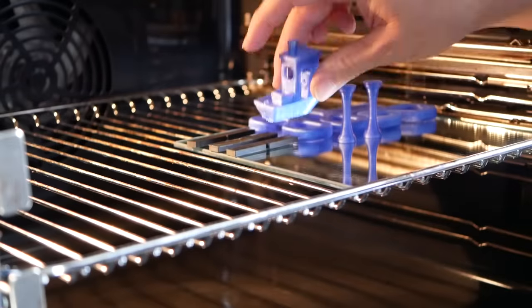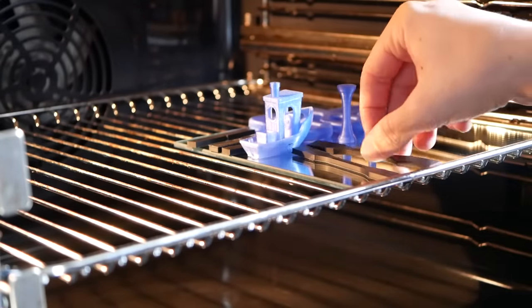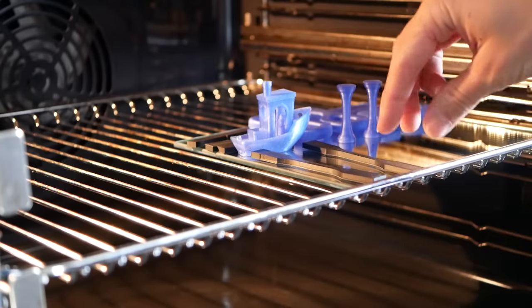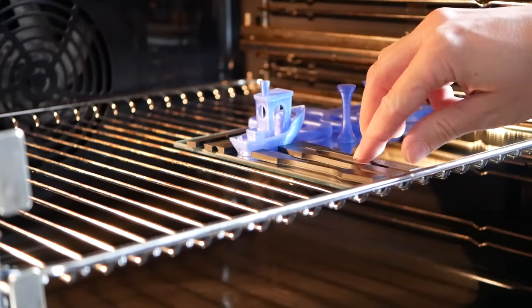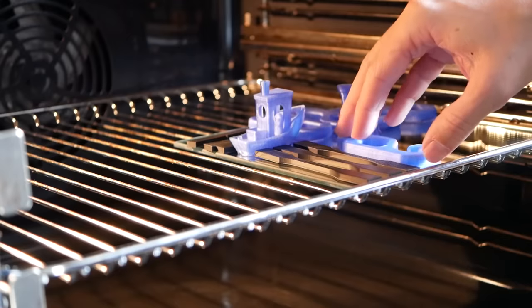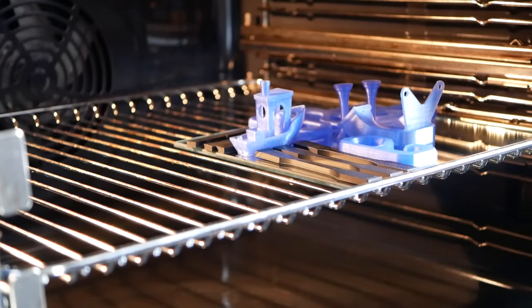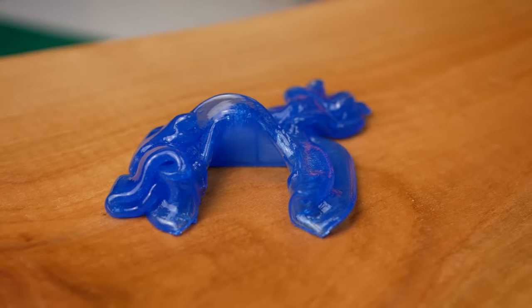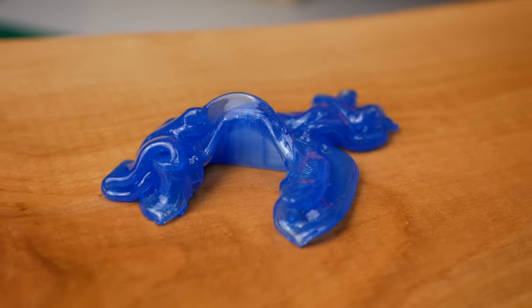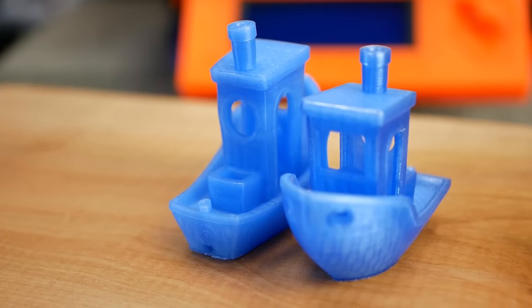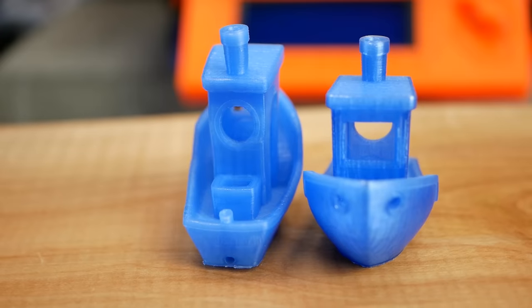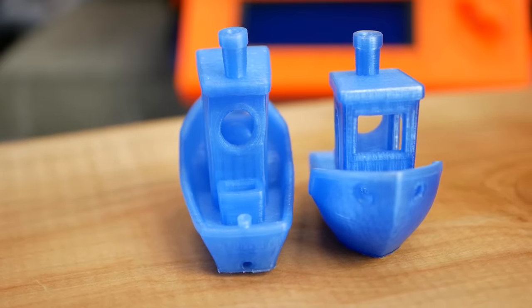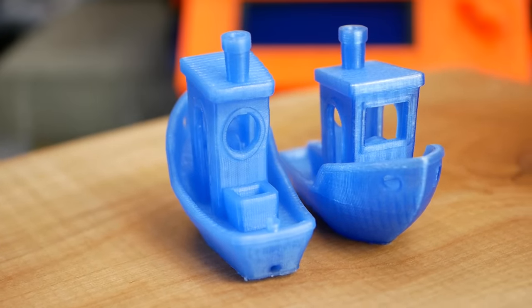I don't really know if I want to call annealing PLA busted at this point. Well, this process definitely improves the thermal resistance of the materials significantly, but in terms of mechanical properties, the gain of around 10% is in my opinion only very small and I have definitely not seen anything in terms of fusing the layers together. I'm sorry to give this verdict. My research hasn't brought up any way to fuse these layer boundaries together without remelting them. This is especially all overshadowed by the warping problem that you usually have when annealing PLA. This can be tackled by material choice, stress relief or maybe submerging the parts in tightly packed sand but probably still will cause you issues.